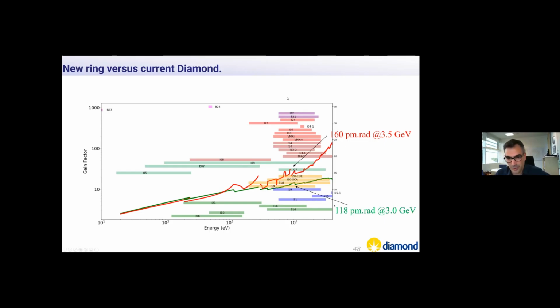And this plot is very busy, but this is the photon energy. Each bar represents the energy range in which the different beamlines operate. The green and red curves show the gain factor in brightness that you can get with the first upgrade, which keeps the energy at 3 GeV with a more aggressive emittance, and one where you relax the emittance but increase the energy. And it's pretty clear that in this regime there's another factor of 10 to be gained by doing the upgrade at this energy.